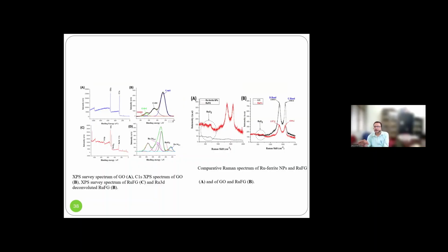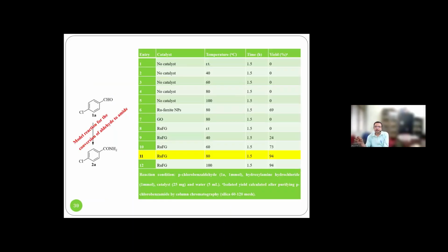The presence of ruthenium is identified. Is the oxidation state also identified? Everything we checked. Then we applied it in the synthesis of aldehyde to amide, and this is the standard protocol. RuFG at 80 degrees, 1.5 hours, it gives 94% yield.